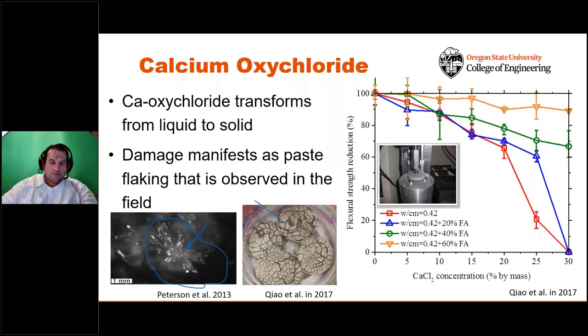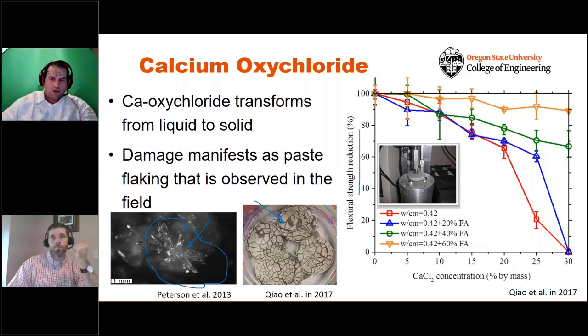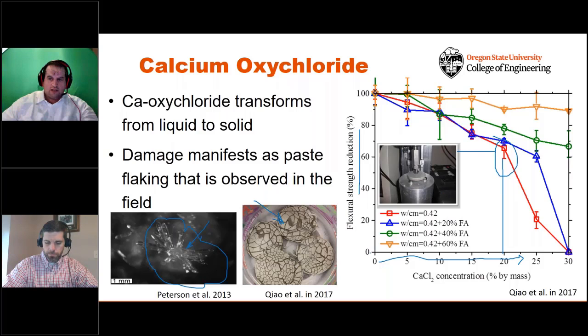These are some samples simply dropped in a calcium chloride solution. I think they've been sitting there for about 10 days. You'll notice this beautiful cracking and crazing on these. We did nothing other than place these in the solution, right? And what you'll notice is the flexural strength, right? As you start to increase the icing salts that are being used, you see the flexural strength can really drop off. By the time you've gotten to about 20% calcium chloride, you see that you're at 60% flexural strength after about a week or 10 days. And then if you go higher than that, the strength goes almost all the way down to zero.